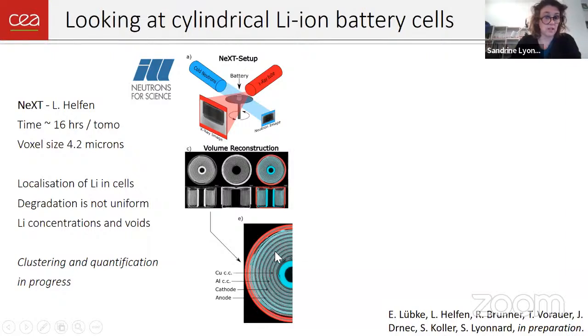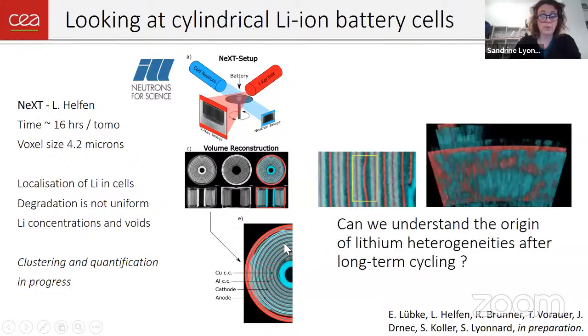We can look at the degradation and see it is not uniform. We are processing this data quantitatively, but what I want to show today is that we complement this with some X-ray measurements, because we've noticed interesting defects in these cells, like bands of the current collector, as you can see here, and regions where you don't have lithium anymore, that has depleted, not blue anymore.